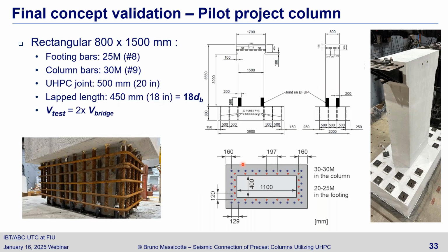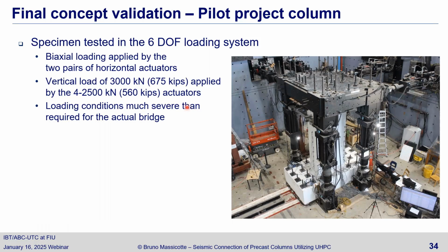So we had bars coming from the footing in red, and the bars going into the column. So all the yielding and nonlinear behavior will be in the bars coming from the footing. And we also use sleeves here just because the column we tested was not exactly the one that was built. It's actually much stronger in terms of seismic behavior, and because of the length, we kept the same length as the designer, so it was 18 bar diameter, which is a bit too much, but we kept that value for the testing. So it was tested again under axial load and load coming from 2 sets of actuators.